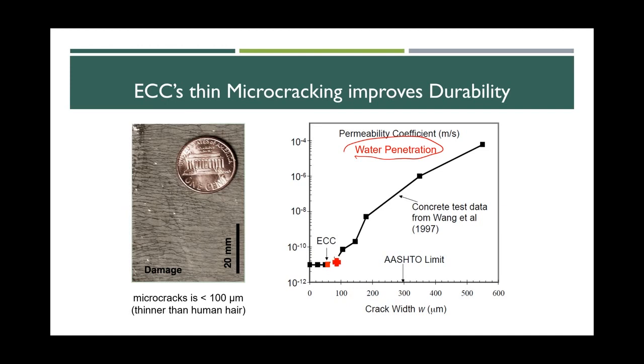So you can see the ECC, compared to non-cracked concrete, has the same water permeability, so it's very tight. But once the concrete is cracked, especially beyond the AASHTO limit, which is a federal highways requirement for cracks, about 300 microns, like the thickness of 3 hairs side by side, you see the permeability goes up hundreds of thousands of times more. So it's about 4 or 5 orders of magnitude compared to non-cracked ones. So the thin microcracks improve the durability of ECC.